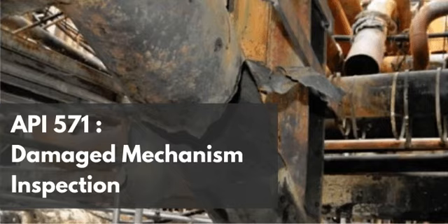The cold work fittings. Yeah. When we look at highly cold-worked fittings, specifically elbows and reducers, the cracking behavior changes completely. Documented failures in these components show cracks extending more than 3 inches or 80 millimeters away from the weld. Yeah, it's a huge difference. A pipe elbow isn't seeing the intense, localized thermal gradient of a weld. So why does the danger zone suddenly expand so dramatically in these fittings? It makes sense that the heat-affected zone right next to the weld is vulnerable, but why do elbows extend that danger zone out past 3 inches?